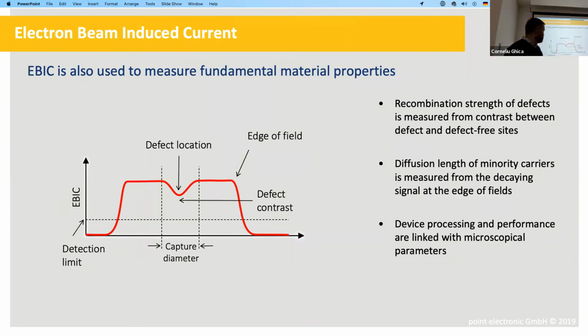Where we have a defect, let's say that the defect is in the middle of our field, then there will be a competition between separation of electron hole pairs due to the field and then recombination, non-radiative recombination. And therefore, we will start to lose some of the induced electrons and we will see a small signal. So we can see the defect is electrically active. We can also see how active it is. We can measure the contrast of this signal, so how much signal we're losing because of the recombination. And also we can see a capture diameter, so how much around the dislocation is effective and so on.